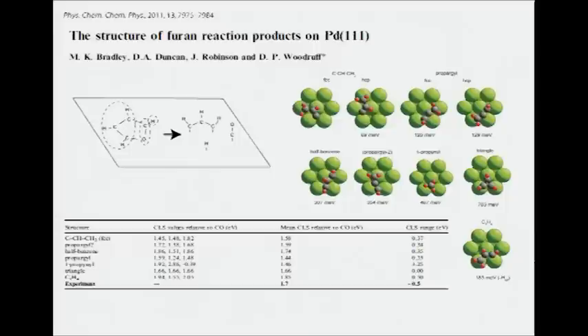So you can do DFT and find all sorts of different conformations with different relative energies. But one of the things, of course, is that you've got 3 different carbon atoms in here, and you can calculate what the core level shifts for those should be, and at least see how they correlate with what you see in the spectrum. What you see in the experimental spectrum is just a slightly broad peak, but that tells you the shift can't be bigger than a certain amount and can't be less than a certain amount. And it actually allows us to eliminate some of these models, 2 in particular, one which shows no shift and one which shows far too big a shift.